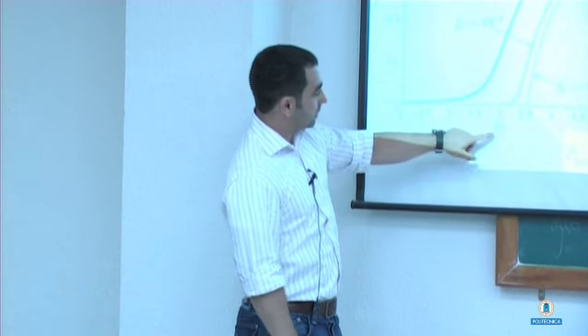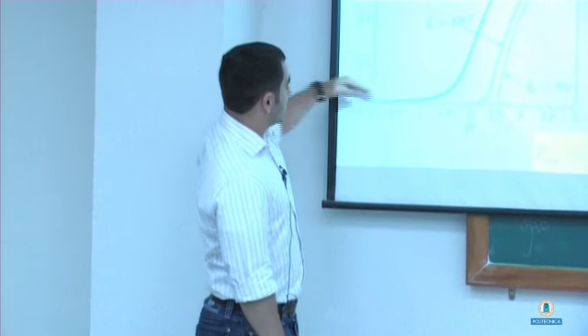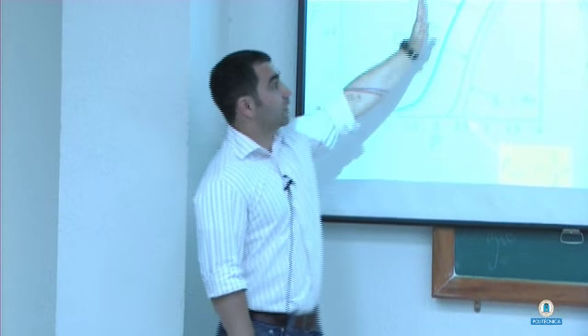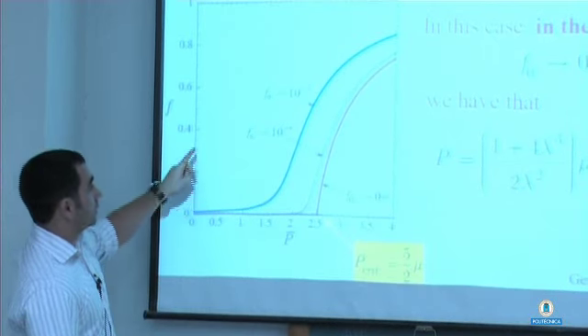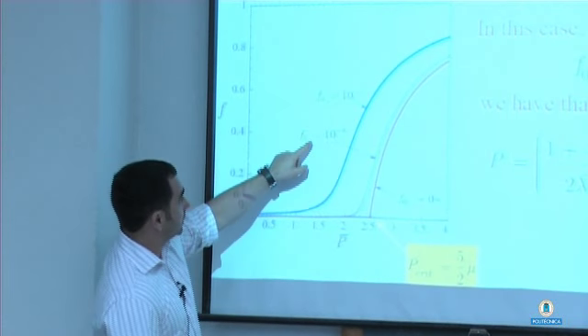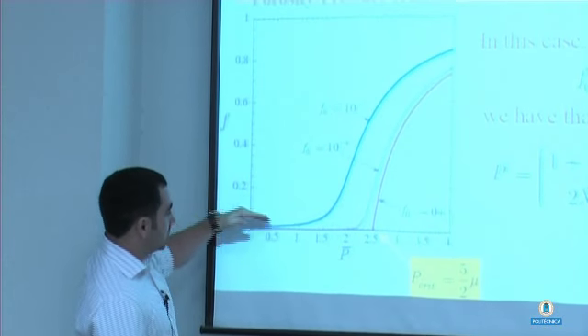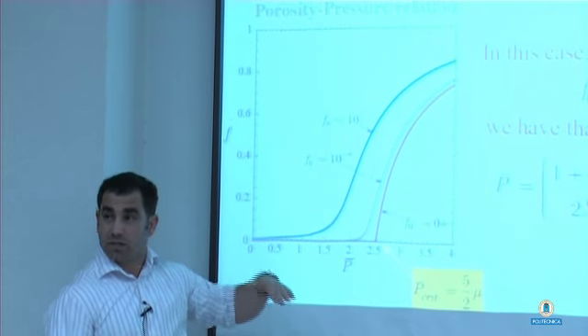So let's see what happens with the porosity as a function of the applied pressure when we decrease the initial porosity F naught. So you see that initially nothing happens, the porosity does not grow much, and at some point it grows very fast, right? So the porosity has to be between 0 and 1. Now you start to decrease from 10 to the minus 2, 10 to the minus 4 the porosity, and this behavior is the same but becomes sharper.